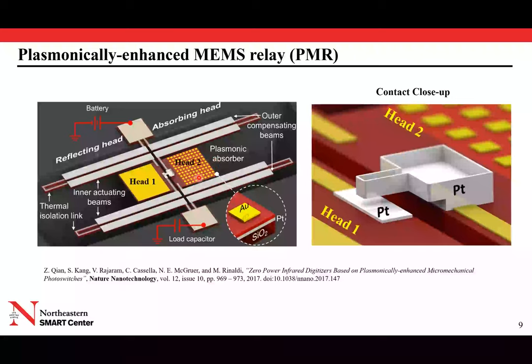As you can see here, we actually have two cantilevers facing each other. Each cantilever is formed by a head and an inner pair of thermally sensitive legs. But there is also an outer pair of thermally sensitive legs, and these two legs are separated by this thermally insulating link, right? Now, the head of the cantilever that carries the contact tip also has an integrated plasmonic absorber. I'll talk more about that later. But you can see here it's a metal-insulator-metal structure, a few hundred nanometers thick, in which we pattern the top metal layer in a way that we can selectively absorb specific wavelengths of infrared radiation. On the opposite head, instead, we have a reflector. And there are also other configurations that we'll discuss later.